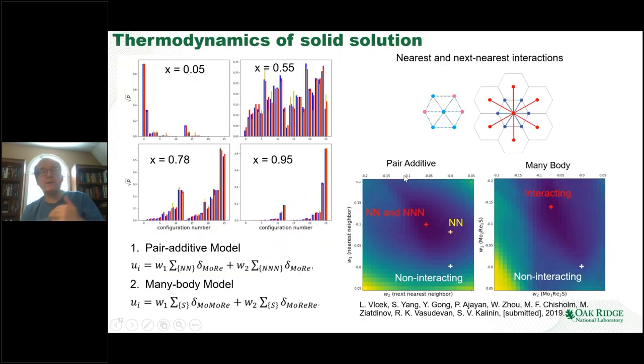So I can imagine that for a second I forget about physics and just take the atomic coordinates of the rhenium and molybdenum atoms. I can take these statistics for this composition series, put them in this statistical distance minimization model, and I can recover the two-parameter interaction between the rhenium atoms. I can either parameterize it as nearest neighbors and next nearest neighbors, or I can parameterize it as two-body models. But in both cases, I get the answer that the rhenium atoms are weakly repulsive.